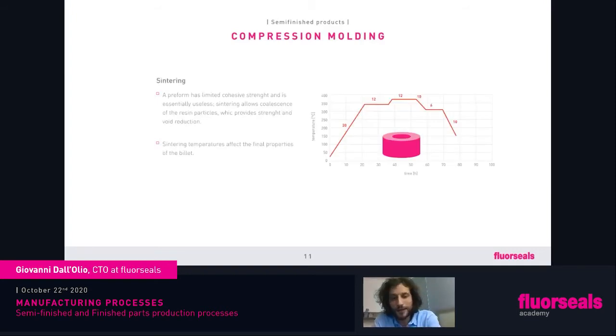This is a typical sintering cycle for 150 millimeter wall thickness tubes. As you can see, it lasts almost 80 hours, almost 4 days of sintering for a 150 millimeter shape. We can see a first part of the graph that is the heating up of the material, where there are 20 hours to heat up the material to a temperature around 350 degrees.